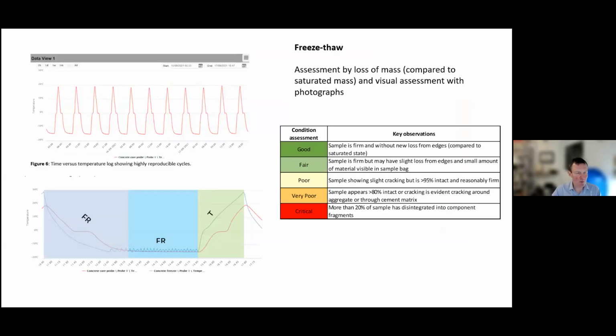Here we have what those probes are telling us. So the top left is like a heartbeat. We have time on the horizontal x-axis, and we have temperature going from -15 degrees to nearly +20 on the y-axis. And you can see it's incredibly regular. Every 6 hours, this freeze-thaw chamber will bring all the concrete through the cycle, and you can move the probe around and see the same response on a pathway shown by the lower image. So you can see freezing, frozen, and then a thaw cycle. It's very, very regular and predictable.